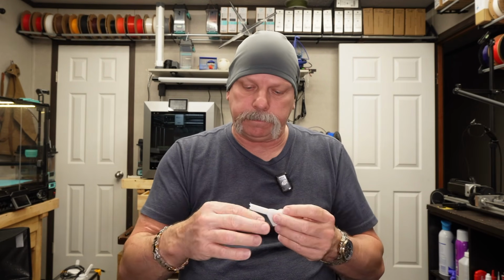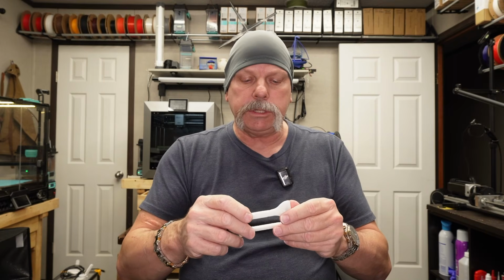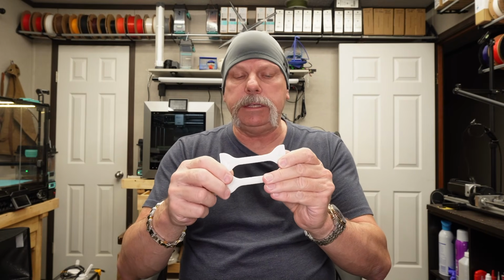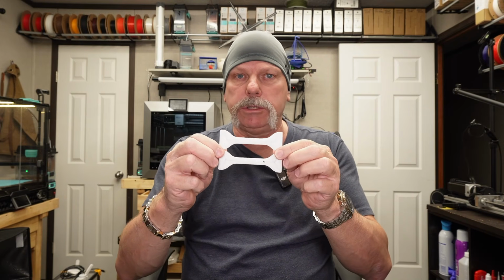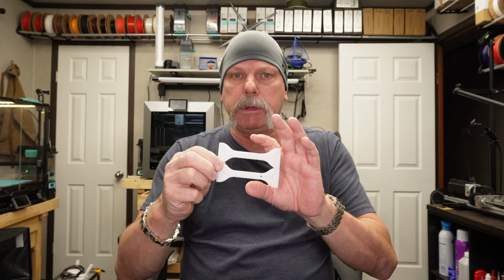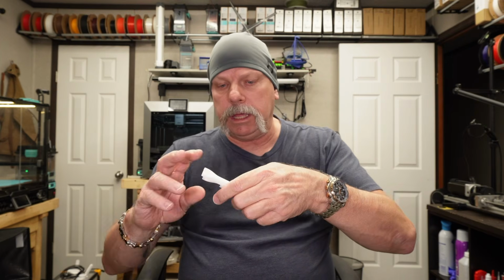This one broke. These 2 did not break, and they did not get down to 50% of the original load before they hit the 6 millimeters of pull. And that's all the further I have it set to go, because on most materials, that's good enough. So that's anomaly number 1 with the PCTG.